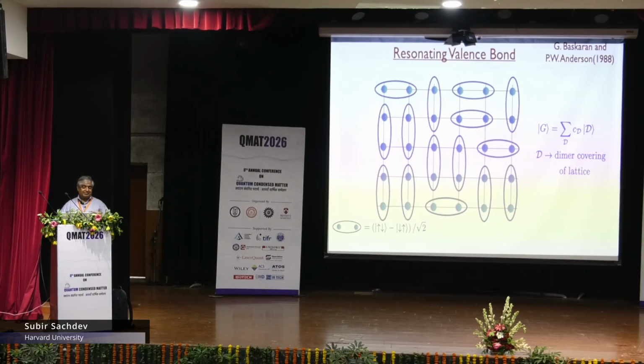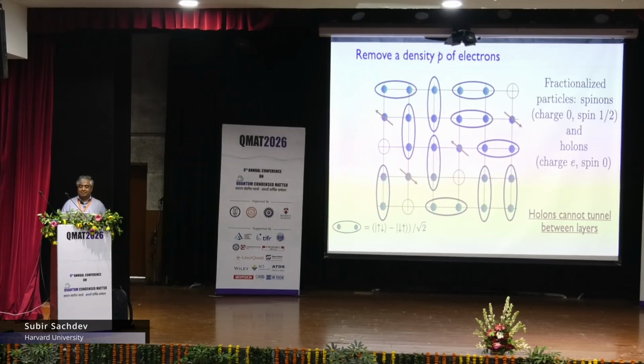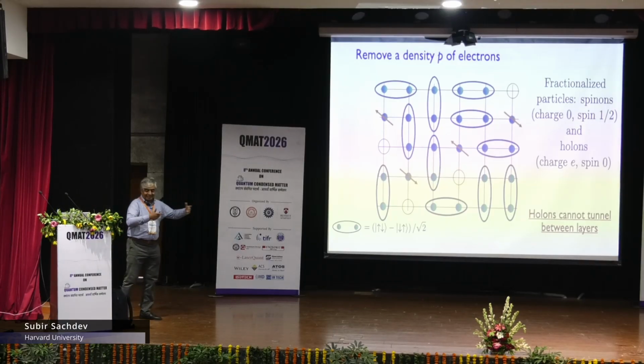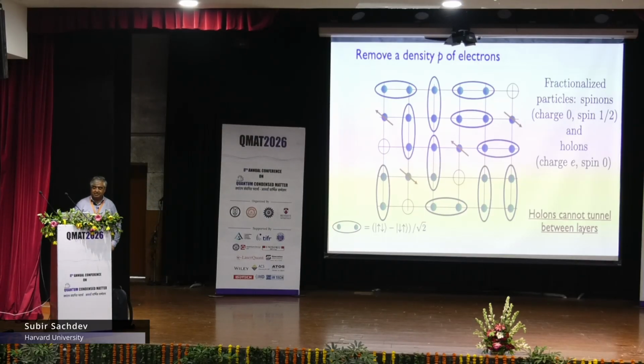So let me give you a simple picture of what this is. Here I want to start with this famous resonating valence bond state of Baskaran and Anderson, where you imagine in the insulator that the spins form these singlets, and the singlets resonate in many different configurations. But we want to remove some electrons. We want to dope the system. And you dope them by removing electrons here, and you get these vacancies, which we call holons, and also an unpaired spin, which we call spinons. So now you can have these spinons and holons moving independently of each other. So those are fractionalized particles, which in one case carry charge but no spin, or they carry spin but no charge. And much of the work in the early days in the cuprates was thinking about the dynamics of these materials as an origin of understanding this mysterious pseudogap region in the phase diagram.